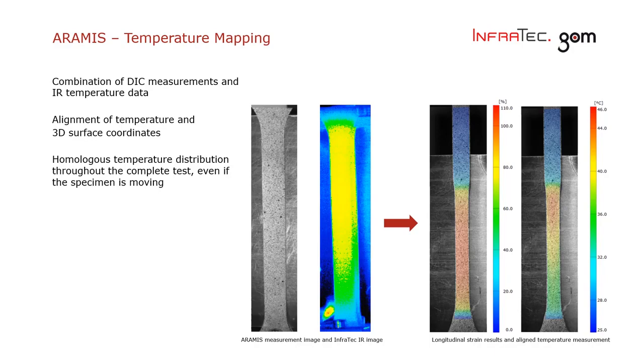And the idea is to bring both together, align that together to get a homologous temperature distribution throughout the complete test, even if the specimen is moving. So the idea here is to be able to evaluate the strain or the displacement results at the same time as the temperatures, and to see where temperatures happen on the specimen and where they move throughout the test. So this enables in the end the separate evaluation of the thermal and mechanical deformations which are going to happen for your applications. So a main important issue is to do the alignment of the temperatures and the 3D surface coordinates.